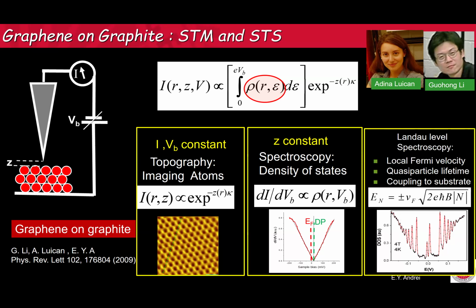Yeah. Okay, so this, you apply magnetic field, and you see these beautiful Landau levels pop up, the square root dependent on B. Now you see there is a gap here at n equals 0, to your question. So we could not understand where this gap came from. The gap actually survives at 0 magnetic field, there's a 10 millivolt gap. So we wondered, is this an excitonic condensate, or is this because we have alignment, we're breaking the symmetry, and we couldn't tell. And the only way to tell was to get rid of the graphite, to suspend the sample. Otherwise, we had no idea what this is. We were really intrigued by this gap here.